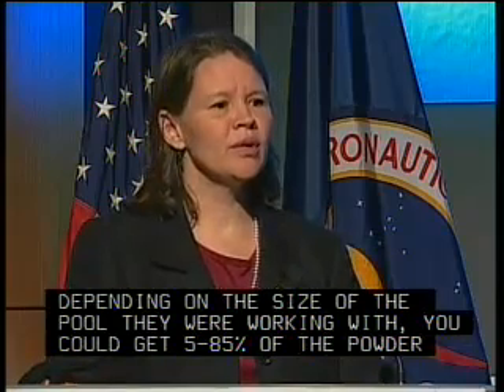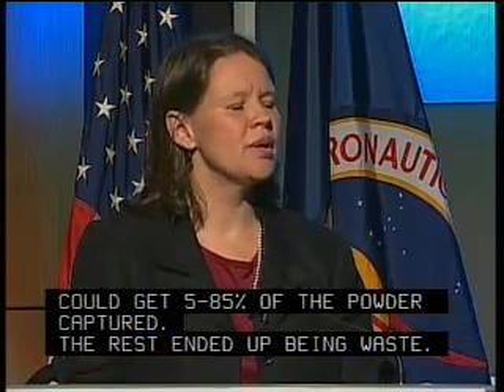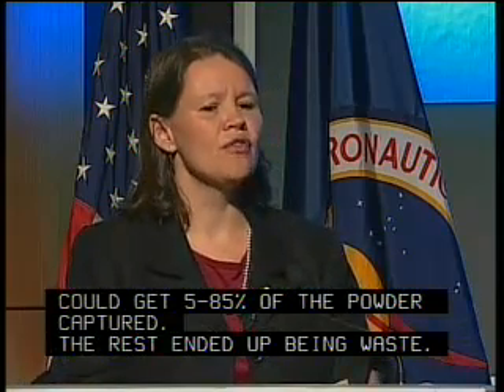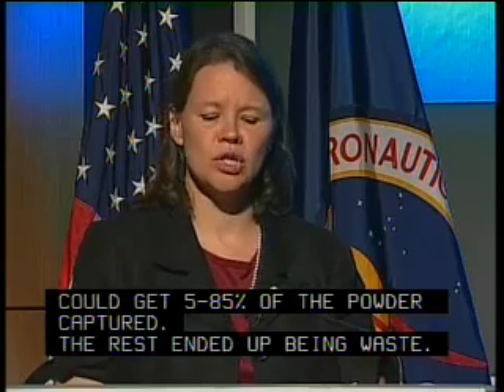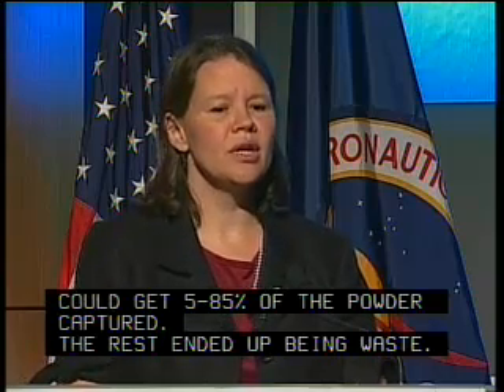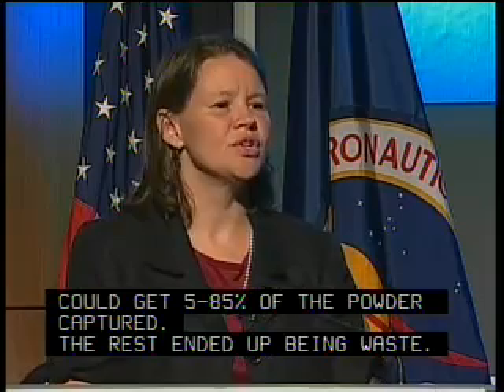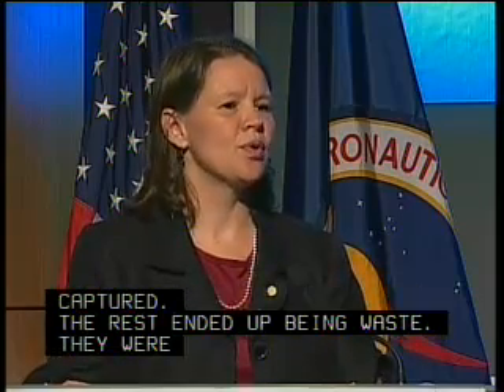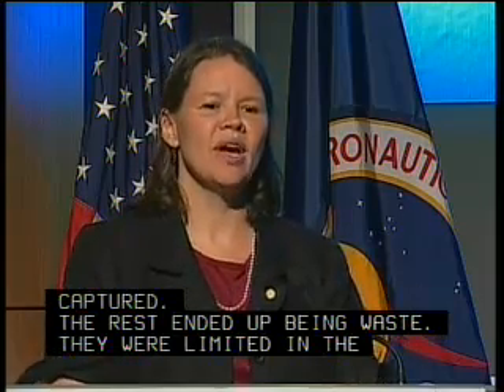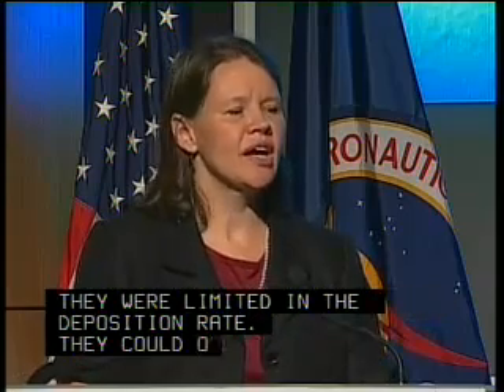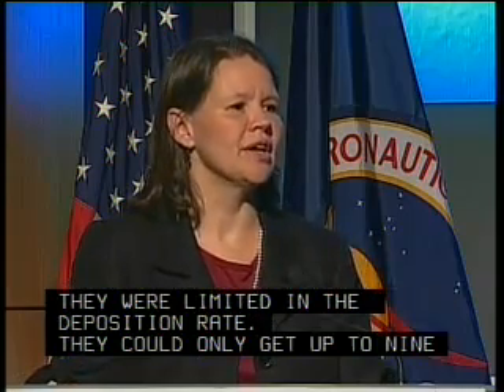And what really prevented laser deposition technologies from taking off in the commercialized world is the fact that they were limited in the deposition rates. They could only get up to, at the most, 9 pounds per hour, but most of them were down in the half a pound per hour. It's just not an economically feasible or viable technology.